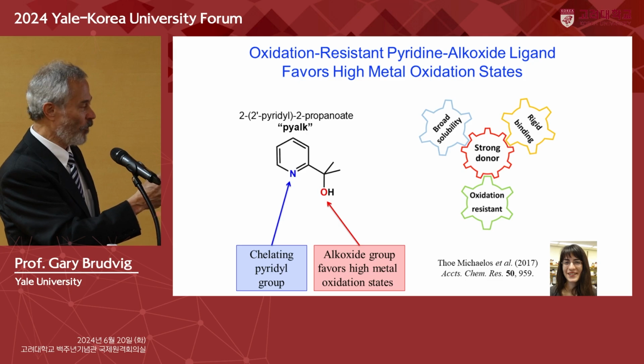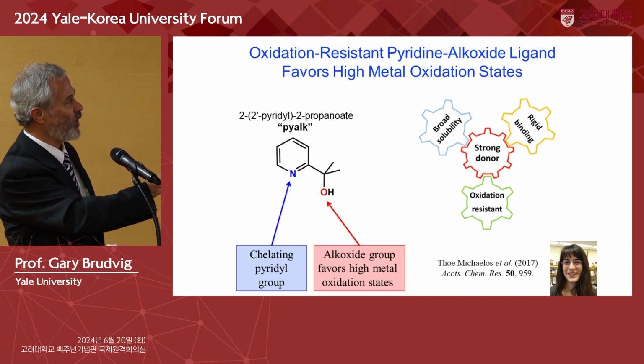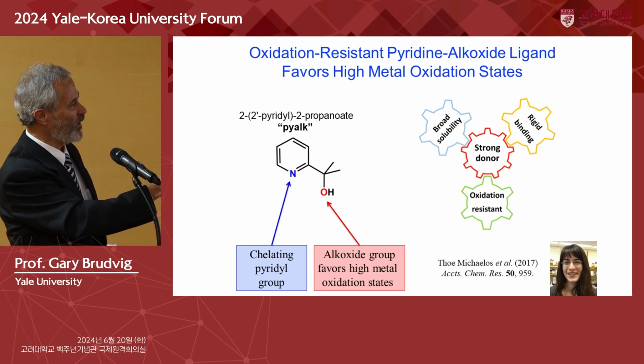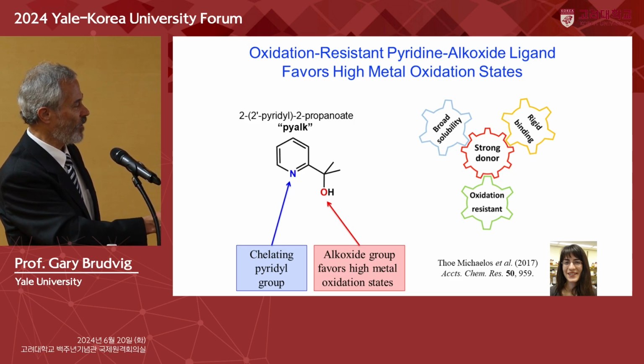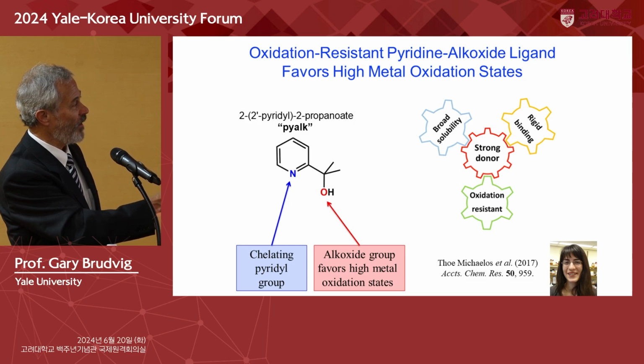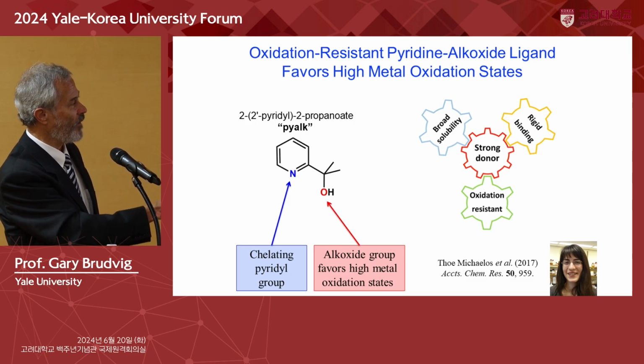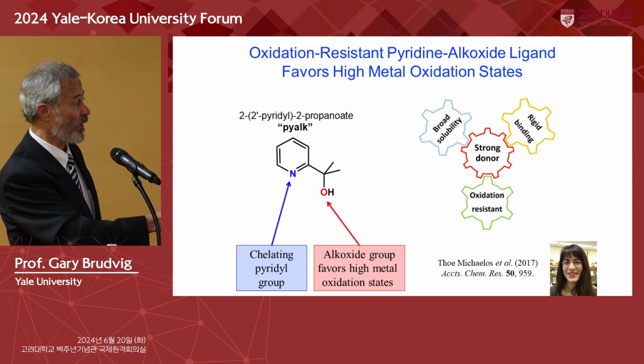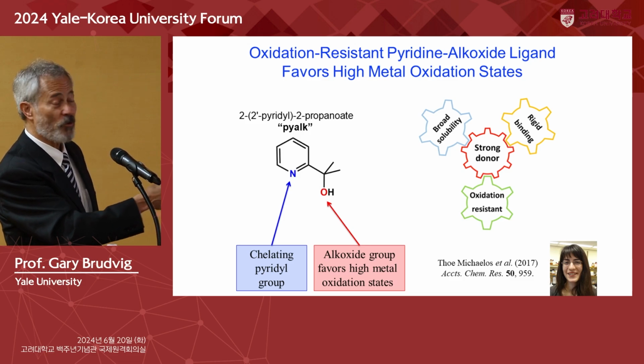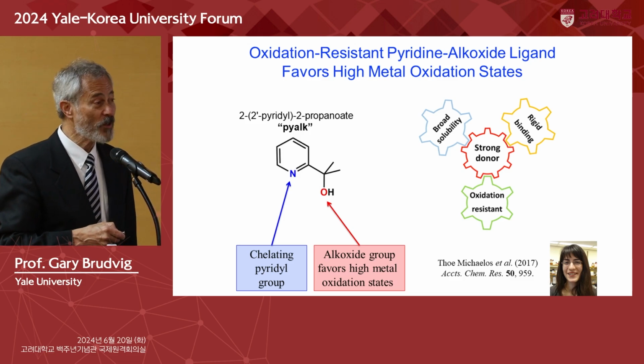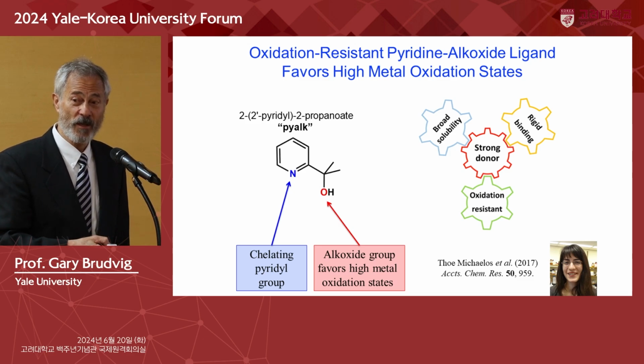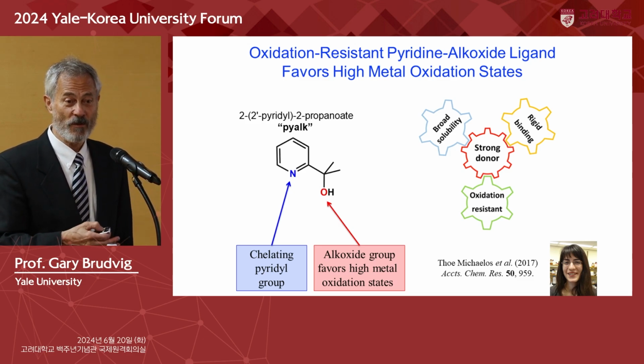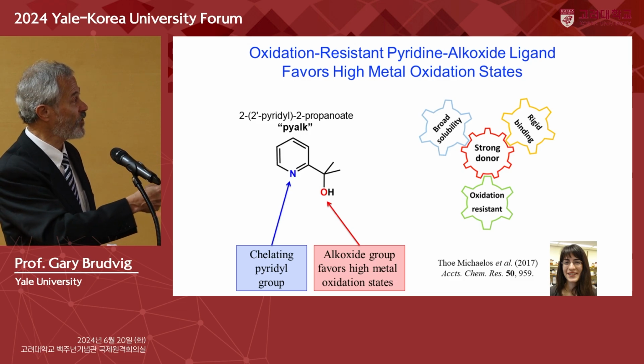And we've looked at a lot of different ones. I'm going to tell you about the winner. The winner is this ligand right here. It's a pyridine alkoxide. Here's a pyridine group, which has a coordinating nitrogen, and an alcohol group, which has the possibility of deprotonating to form an anionic alkoxide, which very strongly stabilizes high oxidation states of metals. In fact, we've used this ligand to produce previously unprecedented oxidation states of palladium, manganese, and iridium because of the ability to stabilize high oxidation states.